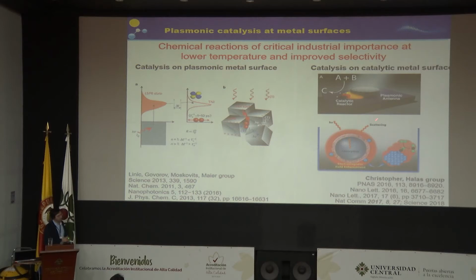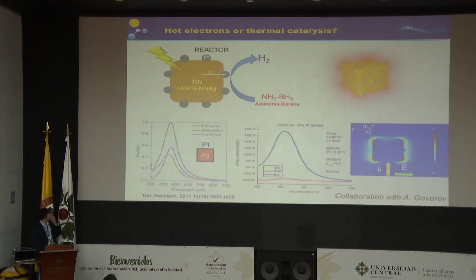Also, this demonstration has usually been performed with silver or gold or aluminum, which is also an alternative plasmonic material that has been developed by Halas group. In our case, we started last year, when I moved to Olomouc in the Czech Republic, to study a titanium nitride platinum antenna-reactor system to drive hydrogen production from ammonia borane.